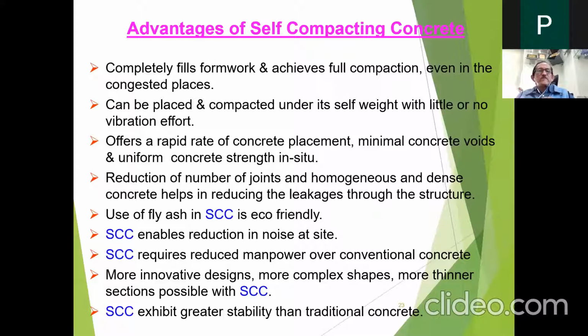So there would be 25%. In 25% time only, we can put the self-compacting concrete. Reduction of number of joints, use of fly ash on a very big scale because you require high paste content. So fly ash use is mandatory. If you are not getting fly ash, then you can go for the slag also. But fly ash is a better option because it is eco-friendly also.